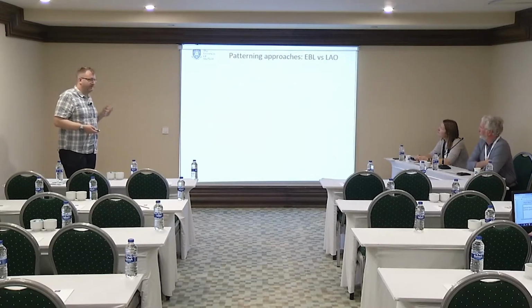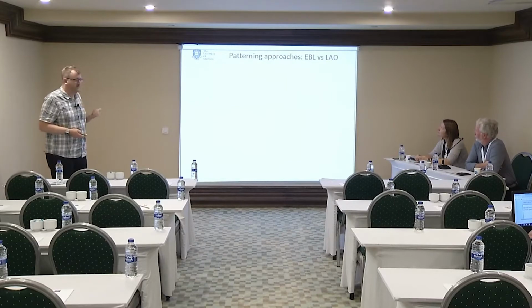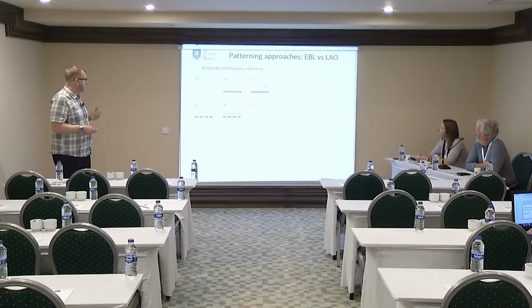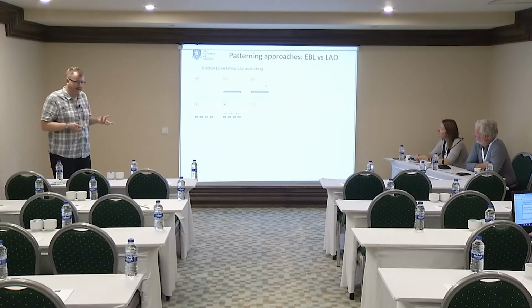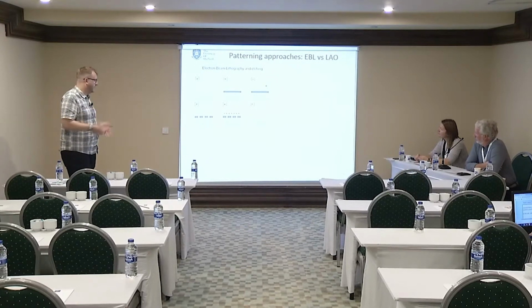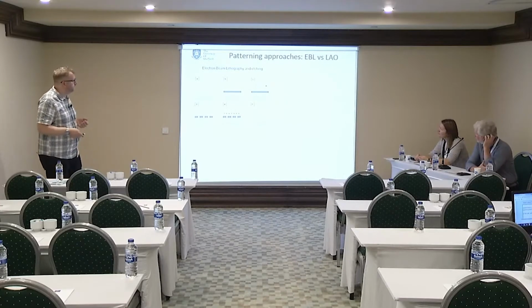There's 2 approaches that we've used so far, electron beam lithography and local anodic oxidation. So electron beam lithography is very much like photolithography. You spin a film of resist on. The difference is that you pattern this resist serially. You go along drawing all over the surface, so it does take time to create openings in the resist. And then you etch using either a wet chemical approach or a dry etching approach to create those pits.